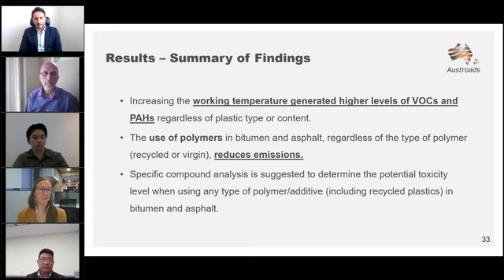In terms of the differences that we've found when extracting binder from field RAP compared to our artificially aged RAP, there were differences in there. In fact, if you remember the slide on the FTIR, there were 3 different bars, and the sulfoxide and carbonyl indices on the field aged RAP were higher than the artificially aged RAP. Now, our method was aimed to simulate, and of course this is not going to be 100% accurate, approximately 10 years in the field.